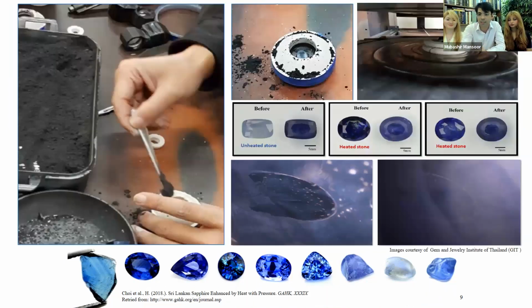And the GIT had these interesting observations. For example, the way they do it, they create these crucibles, fill them with a graphite powder. They put them in a uniaxial press. It's a hot press in practice. It's not a furnace per se. And then they create these before-after kind of conditions. The characteristic telltale signs for them are the ghost fissures, but that is a little bit different. We will talk about that in the third session that we will be talking about during clarity enhancement.